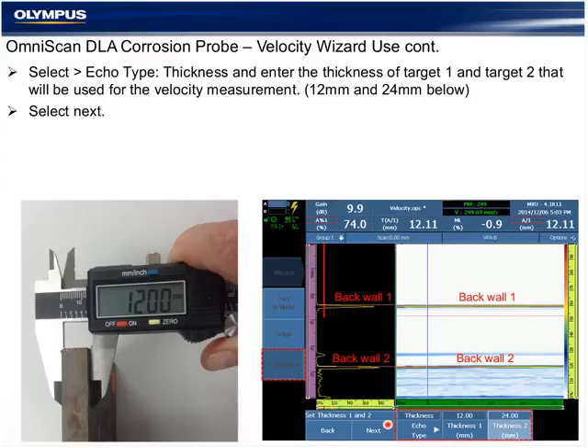And in weld inspection or corrosion mapping, what the OmniScan wizard does, like every wizard of this type, it doesn't calibrate the instrument to a velocity. That's what the old UT analog systems did. What it does is it measures the velocity based on user input. And that measurement is done on one A-scan, one time, and it's completely dependent on the user taking a good measurement and the software knowing the real thickness of the component.